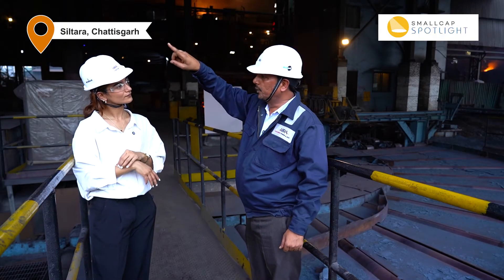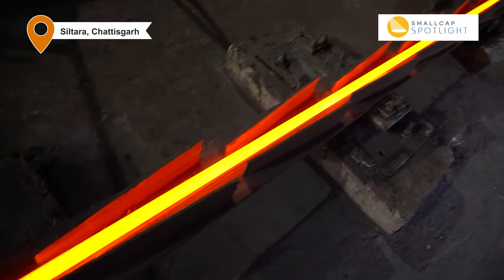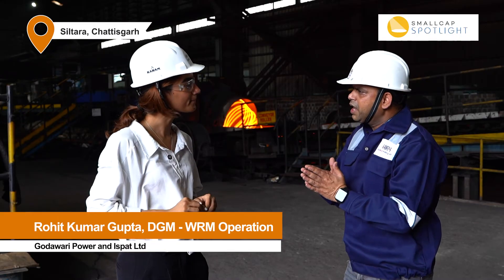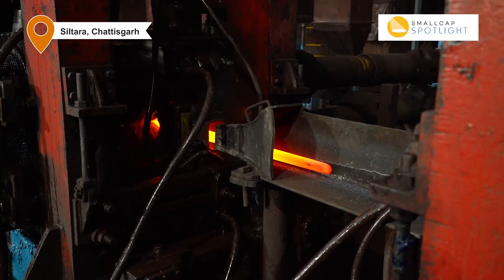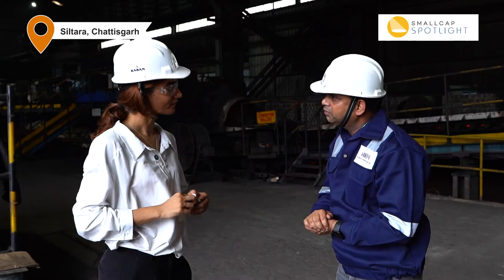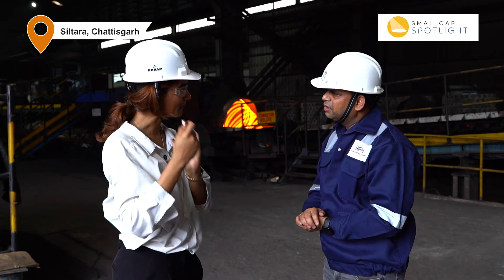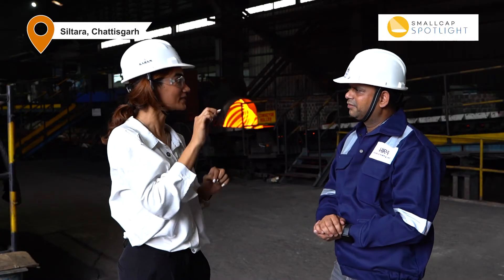This will go straight into the rolling mill. What does the rolling mill do? It reduces the material. The rolling mill has passes through up to 14 stands. In the 14th stand the wire rod comes out at 5.5mm. So basically the billet of 140mm goes through the process and is reduced all the way down to 5.5mm wire rod, and then the wires are coiled.